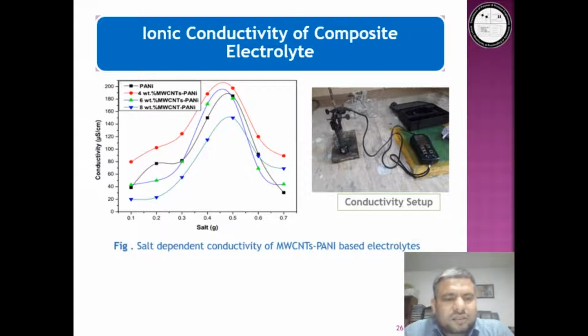Similarly, it shows that salt concentration also affects the conductivity of electrolytes. It increases with increasing salt contents and then decreases with further increase of concentration of salt. The high conductivity value you see on the figure, that is 197 microsiemens per centimeter, is for composites containing 4-weight% CNT at 0.5 gram of salt concentration. So thus the combined effect of CNT and salt increases the overall conductivity of the electrolyte system.